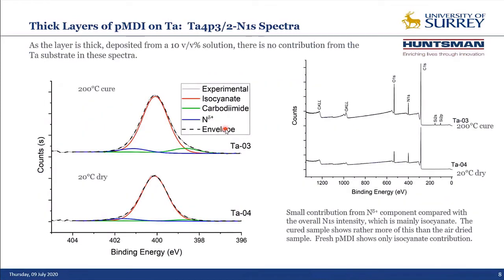And we think we've got the answer by looking at thick layers of PMDI on tantalum. This was a 10% solution that was, a small aliquot, dropped onto the tantalum, and it was then either dried or cured. Here are the XPS survey spectra. We can see carbon, nitrogen, oxygen, as we'd expect from the isocyanate material. Bit of silicon there, that's probably our old friend polydimethylsiloxane. I would like to blame my colleagues that used the oven that we cured it in for this, because it's not there on the sample that's just been dried in our lab.